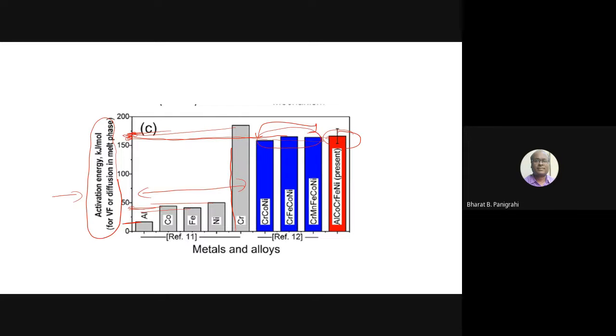This is another way of confirming the liquid phase sintering in our lab, where the viscosity of our alloy and the reported alloys are nearly in the same range compared to their base elements. Base elements have much lower values. So it does indicate that this alloy is melting as a whole and forming a liquid which has a viscosity completely different from their base elements. So this also gives a very important conclusion about the viscosity of the alloy phase and the viscosity of the independent elements.